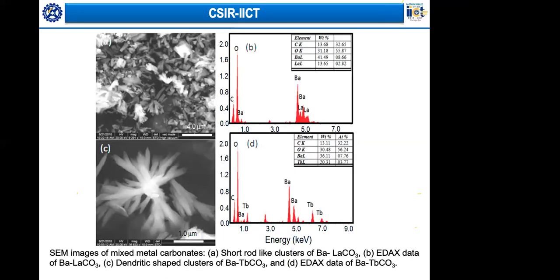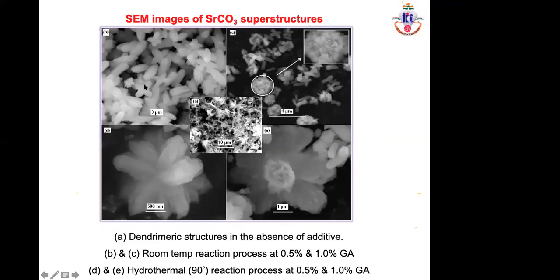So here what we have done is we have taken some rare earth dopants like terbium and lanthanum. When these dopants are taken in such low concentrations, you also see that there is a change in the morphology of these kinds of materials. This is strontium carbonate. Here again, this is without gum. This is with gum, but not normal conditions. This is with the gum at a higher concentration. And this is at hydrothermal conditions with 0.5% and 1%.